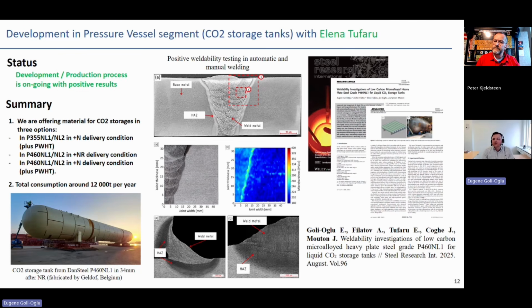If, for example, 50 years ago, the normal level of low temperature toughness at minus 20 was around 60, 70 joules, now we're getting material with impact toughness 200 joules. Wow. Yeah. Same at minus 50. There are different types of technology, where as-rolled material is the easiest, and TM plus ACC is the most complicated. But in TM plus ACC technology, you could get impact toughness of 300, 400 joules per square centimeter. Yeah. So many impact hammers are out of spec when you go above 300. Yes, and that's why we have installed a powerful one with 450 joules. Yeah, okay.